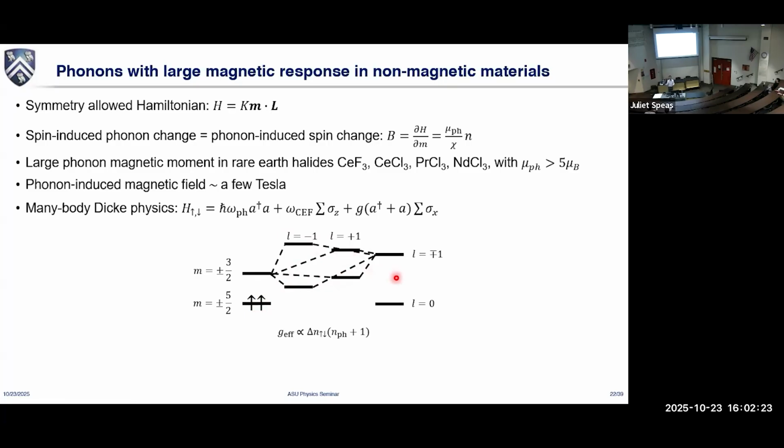Okay, and for this case, there's actually no limit in how much phonon angular momentum or phonomagnetic moment, because as long as the electron is very susceptible to magnetic field, this is true for paramagnetism at zero temperature. So you need an infinitesimal magnetic field to align all the spins. And then all the spin population will generate a giant splitting in phonon energy. So that basically gives you an infinite size of phonomagnetic moment. Okay, so that's basically the mathematical physics here.